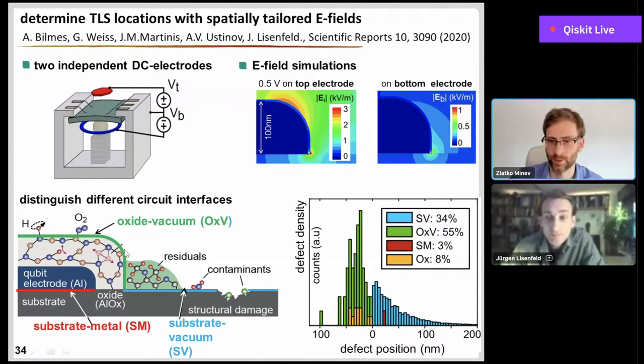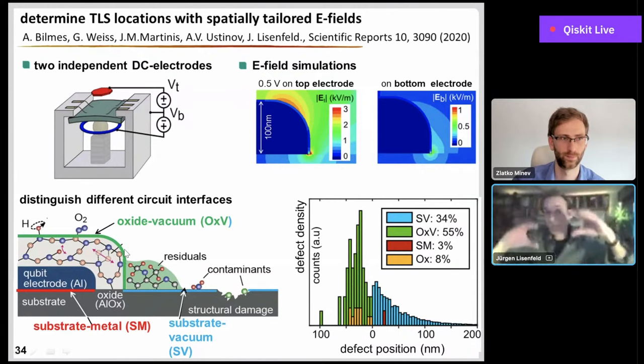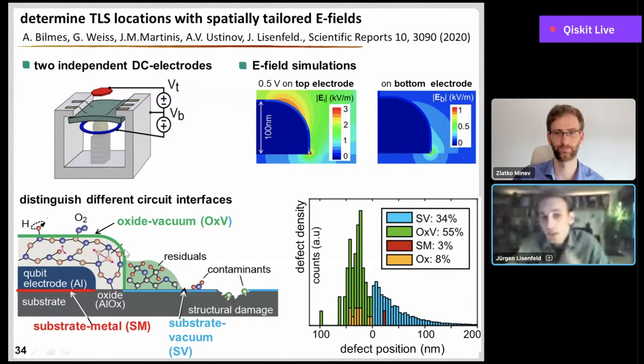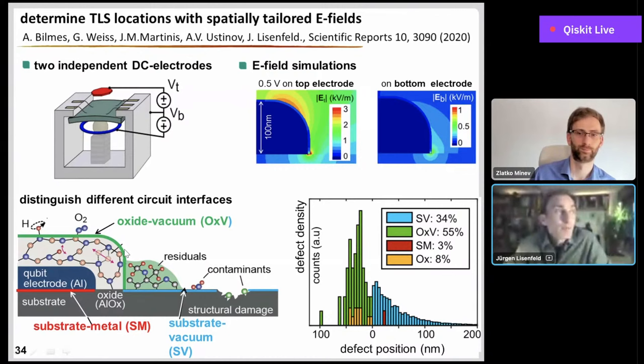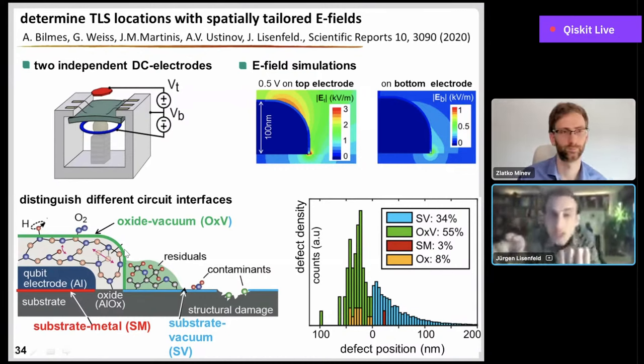Question from Andrew, following up on my question: with that level of strain of 10 to the minus 15 meters, would vibrations at the chip not cause time-dependent changes in the TLS effect on T2 and T1? Well, one would need to think about how much a vibration would actually change the strain inside the material. If it's just a common vibration of the whole thing, then the material itself doesn't necessarily oscillate, or the thickness or the strain oscillate similarly. Just to make sure, the strain change was 10 to the minus 7 in total, not 10 to the minus 15.